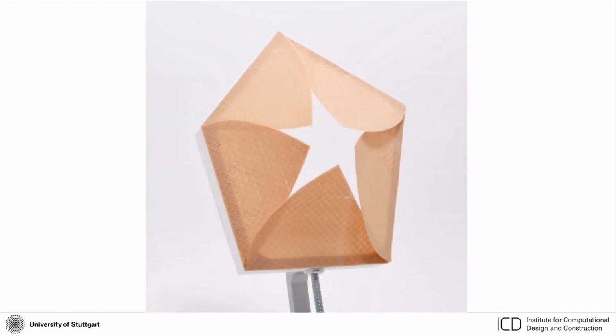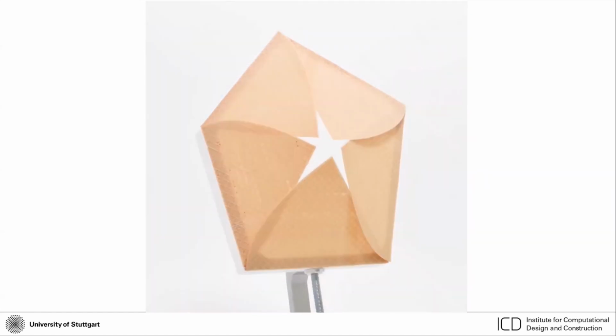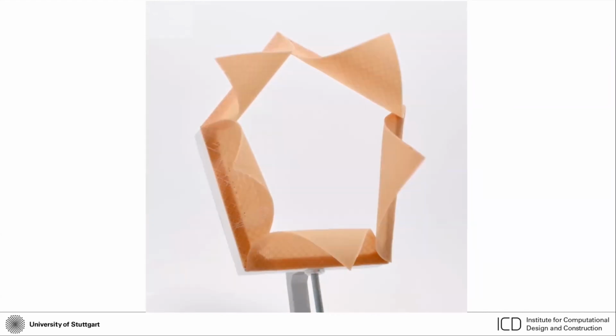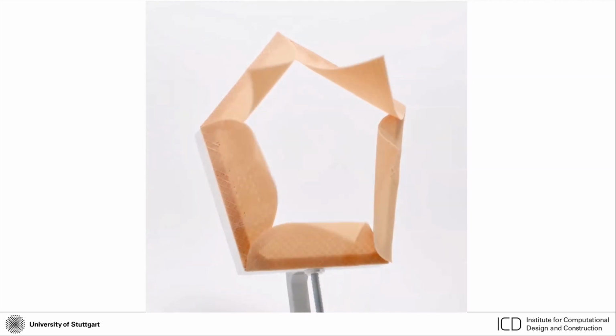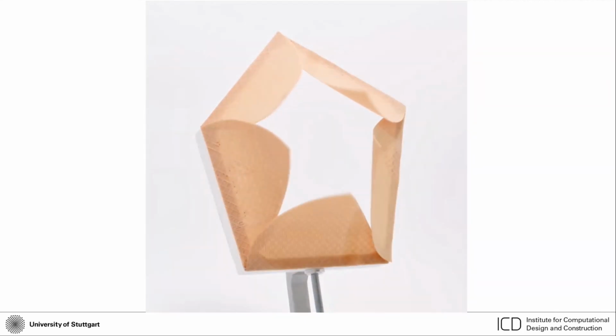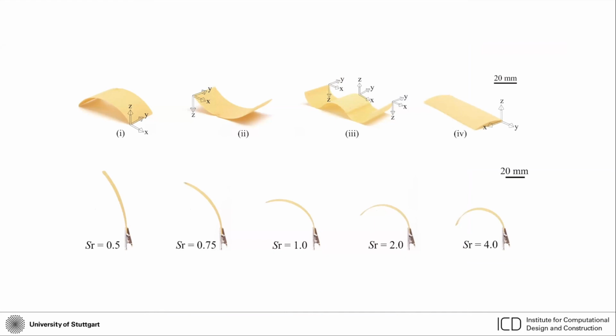Unfortunately, at this point, I cannot share too much because this is now a paper that I need to submit this week. But what I can say is that the 3D printed structures produced by the cellulose-filled filaments are super responsive to humidity, not only to water immersion. They are relatively fast, so they change shape in something like 20 to 40 minutes in the absorption and desorption cycles, and their motion is also cyclic. And of course, because we're doing 3D printing, we can simply program different geometries, different bending curvatures, bending orientations, and so on. And I'm sure that you already know these topics well.